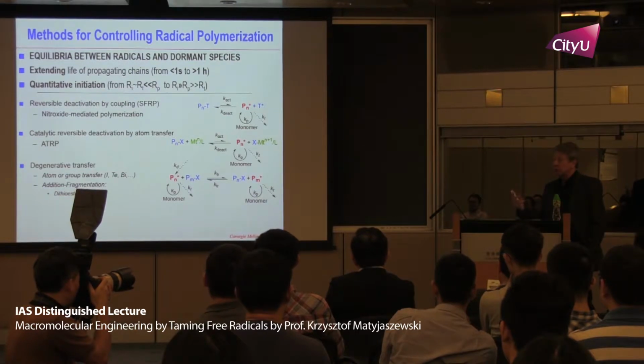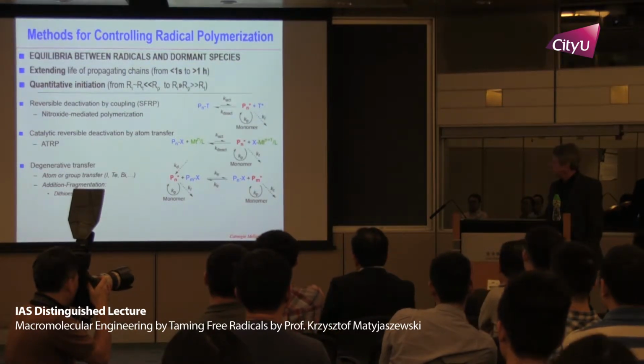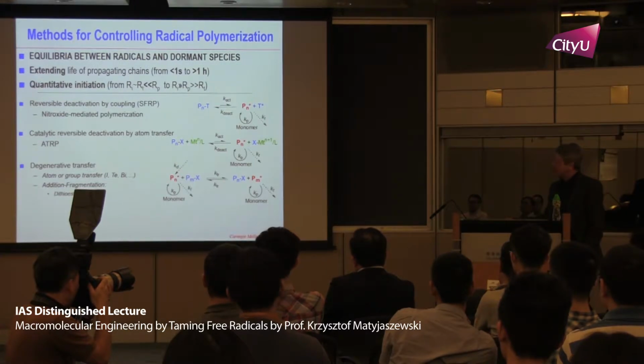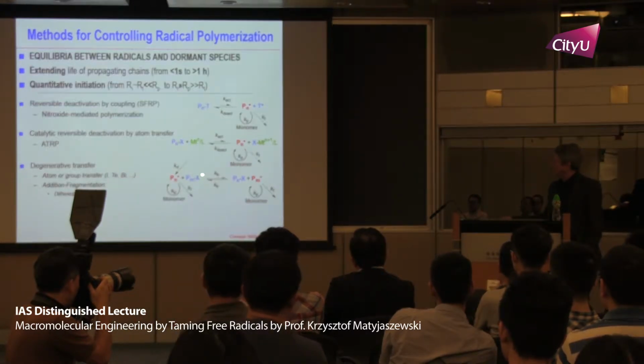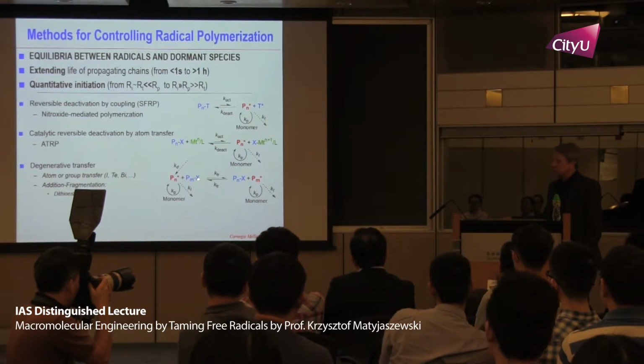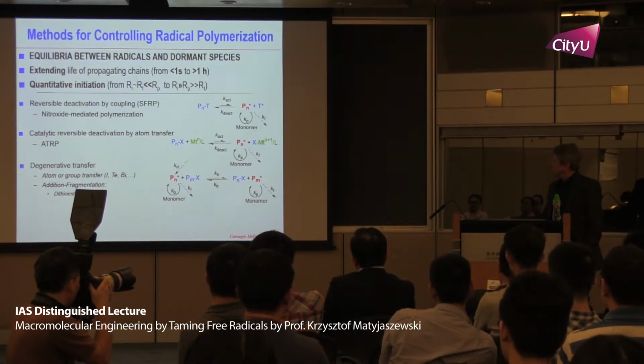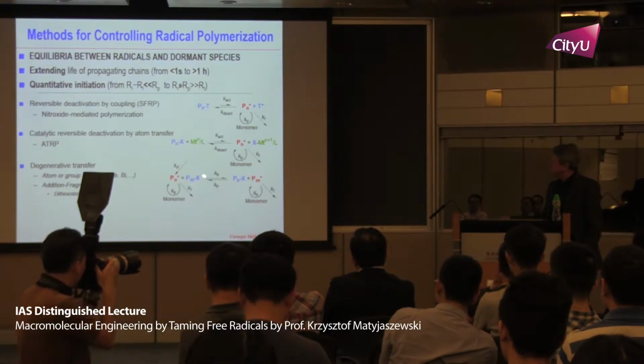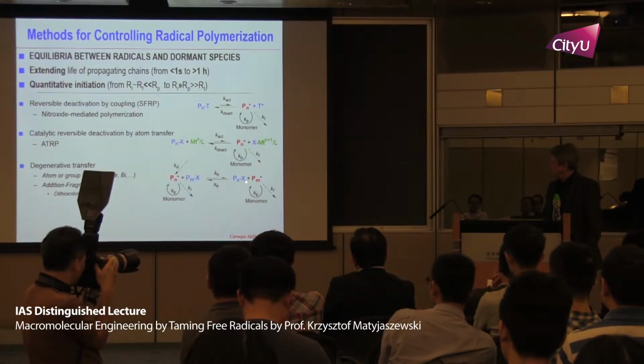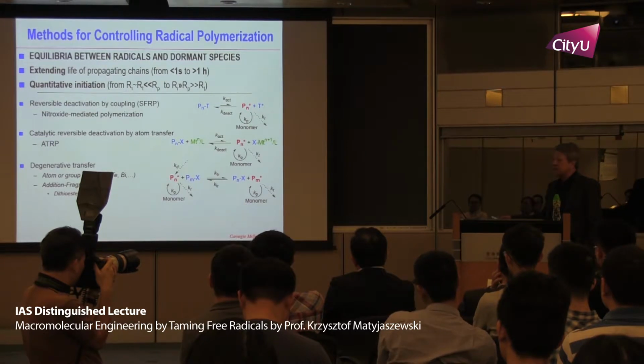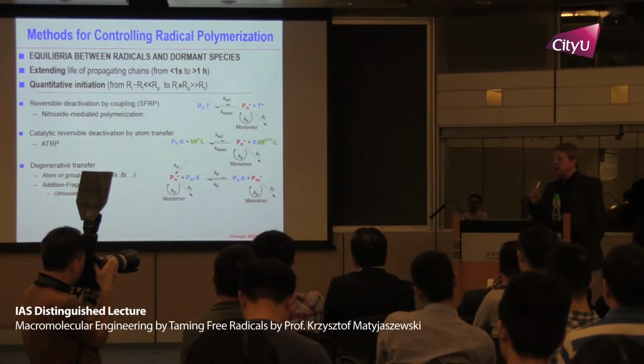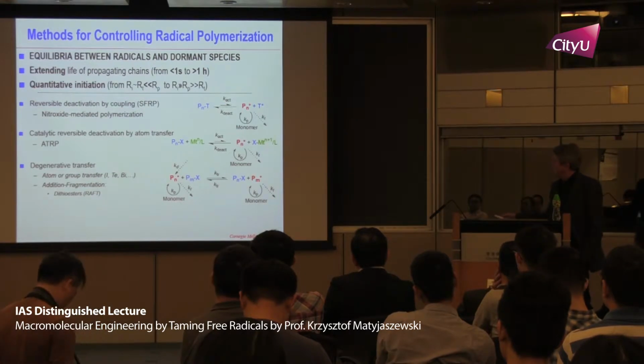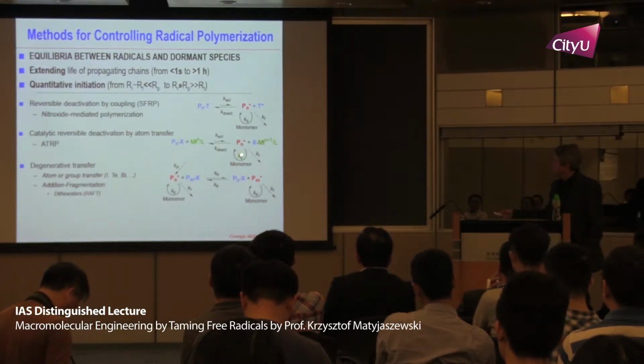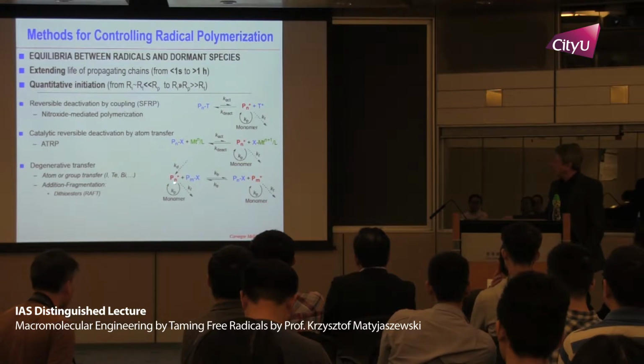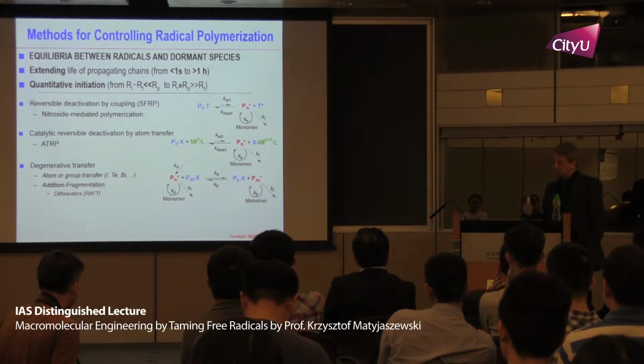You need both. There's also another approach, which is based on degenerate transfer. You have this atom, iodine, or derivatives of tellurium, or bismuth, or dithio compound, which would provide degenerate exchange between active and dormant species. You could see what is on the left side, the right side is exactly the same. So the key of control for all of these systems is how many times you propagate before you deactivate, how many times you propagate before you exchange. And this would define the degree of control.